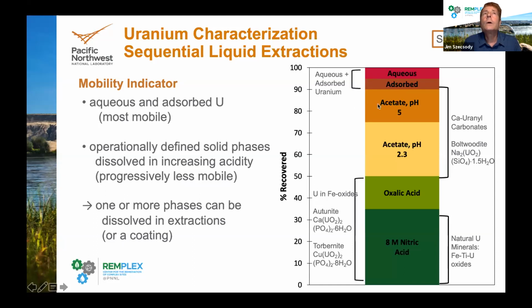So basically we go from weak acids to stronger acids, and one or more phases are dissolved. In general, the weak acids dissolve what I'm going to bin as high solubility uranium minerals: carbonates and hydrosilicates, boltwoodite and uranophane. And then the stronger acids dissolve uranium in iron oxides and phosphates and titanomagnetite, things like that. So in general, the aqueous and adsorbed phases are the most mobile uranium phases, and some of the high solubility phases are mobile. But these phases down here are typically not very mobile.